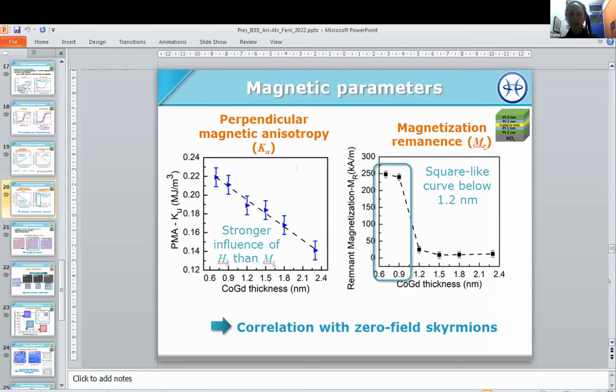We also look at the remanent magnetization, and we can clearly see that we can divide the samples based on the thickness. Below 1.2 nanometer, we have a clear square-like curve with a high remanence, while with increasing thickness we have a really low remanence. And so this has a correlation with having zero-field skyrmions. When we have a high remanence, we are expecting that maybe we have skyrmions that are stabilized even at zero field.